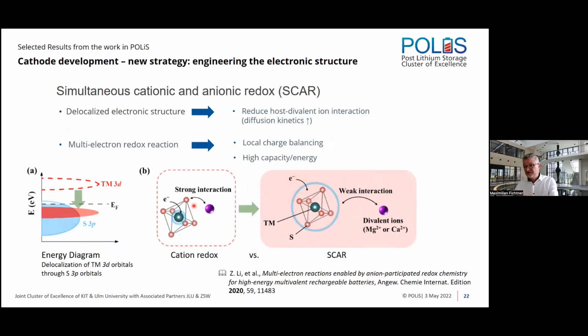If you rather go for another system where the interaction is weaker, in the past this was called soft anions or whatsoever, where you have less polarization, then this may work. And this is basically possible by involving both the electrons from the cations and the anions. If you manage to get a delocalization of both, then you may achieve a redox reaction where not only the cations but also the anions contribute, and this is reversible and leads to a higher storage capacity.